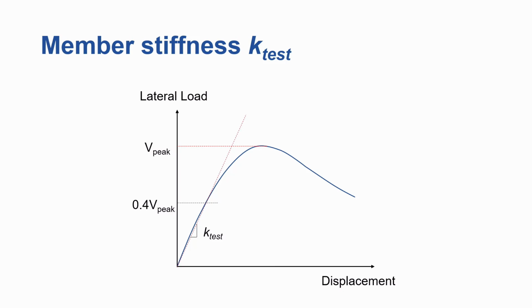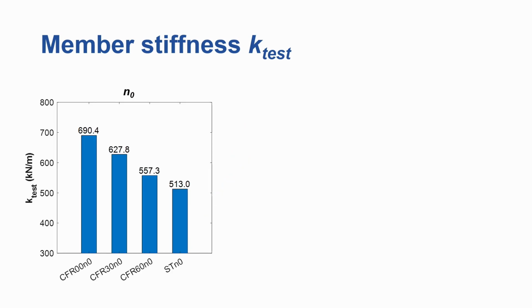Here we looked at the member stiffness. We took this as the secant stiffness, which is basically plotting a straight line from the origin to about 40% of the peak lateral load. So we took those from the lateral load displacement envelope curves. And one thing we noticed, so these are the results for the specimen with zero axial load level. As the rubber content increased, the secant stiffness reduced. And that makes sense because the rubberized concrete has a lower elastic modulus, so you'd expect to see that.